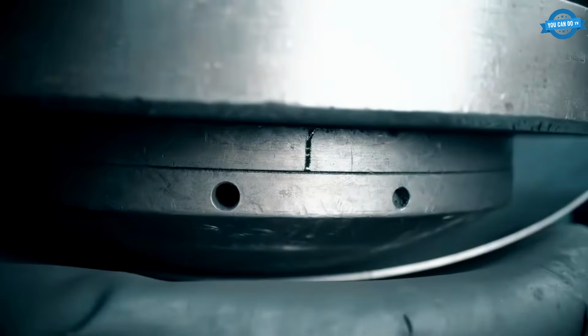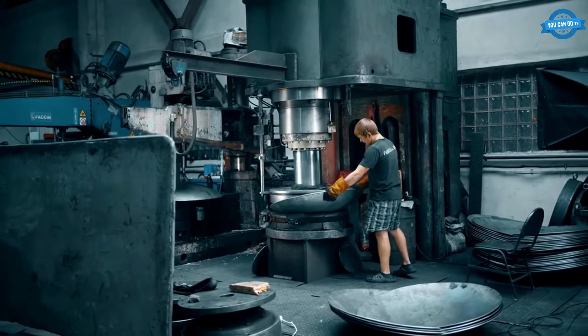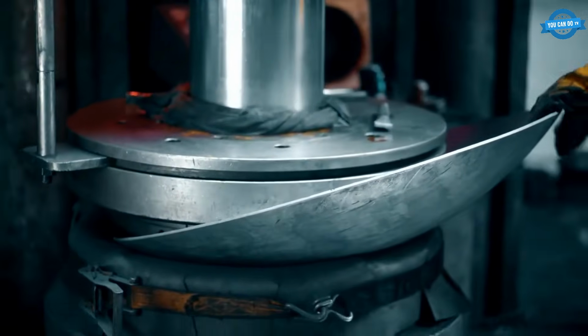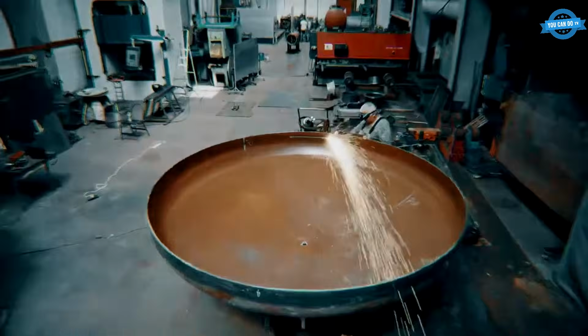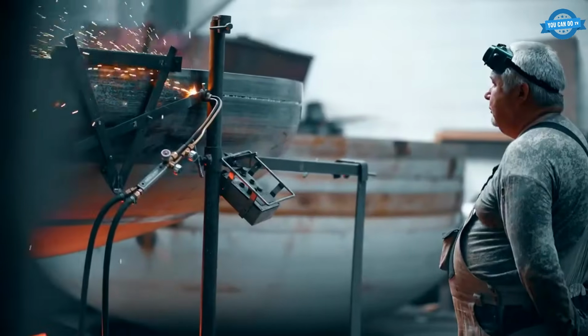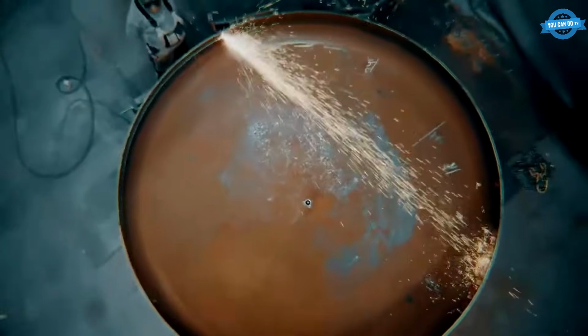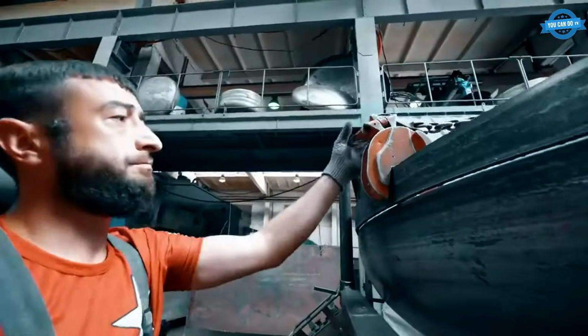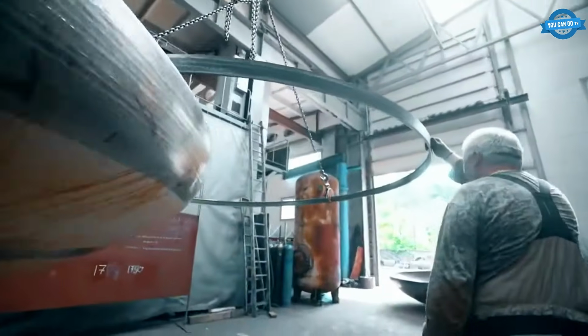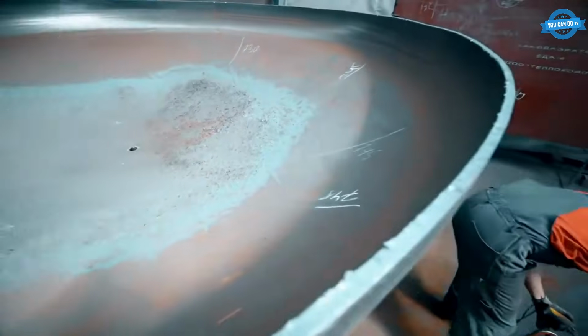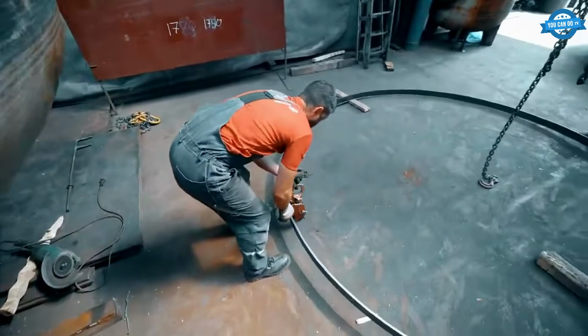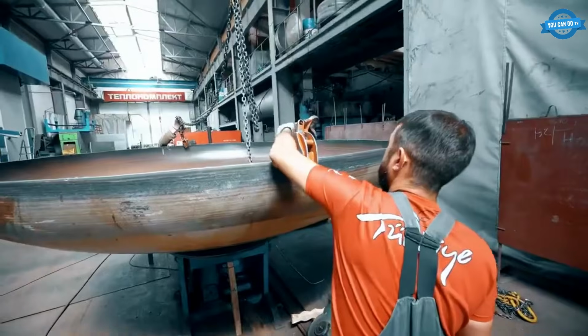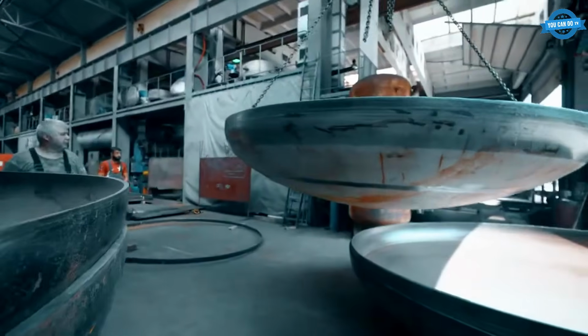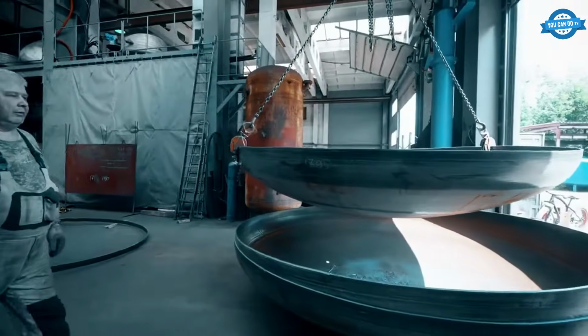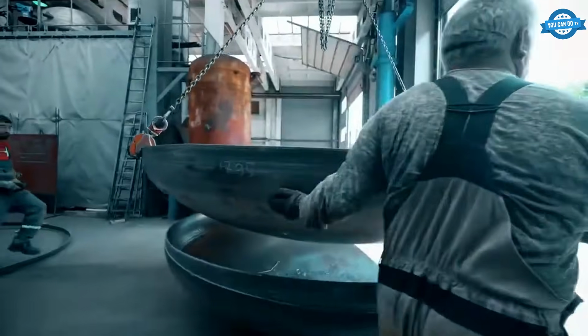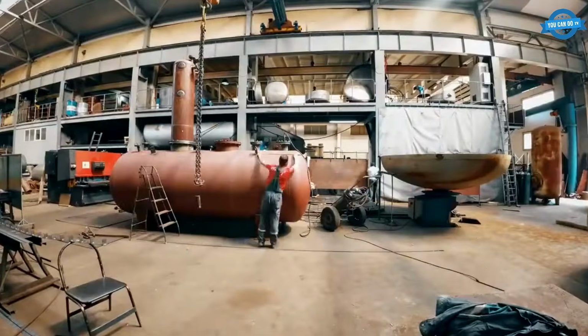Every parameter matters: plate thickness variation, press stroke depth, die geometry. Get any of them wrong, and the finished head shows local thinning or micro cracks that only reveal themselves during hydrostatic testing weeks later after the whole vessel has been welded up. Tolerances are set to industry standards like GOST 6533-78 and 34347-2017. The same specifications that govern pressure vessels across oil and gas, chemical processing, and power generation infrastructure.